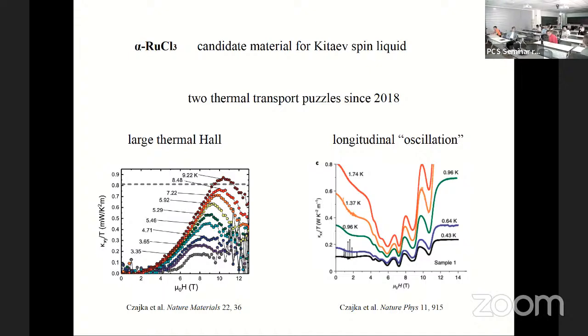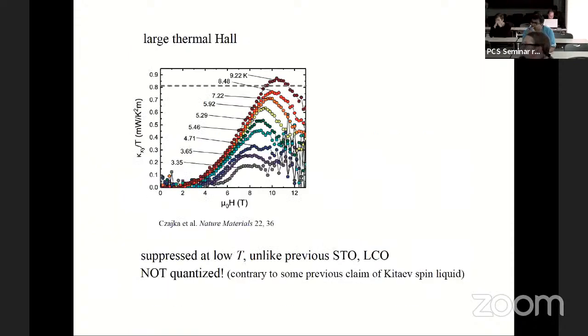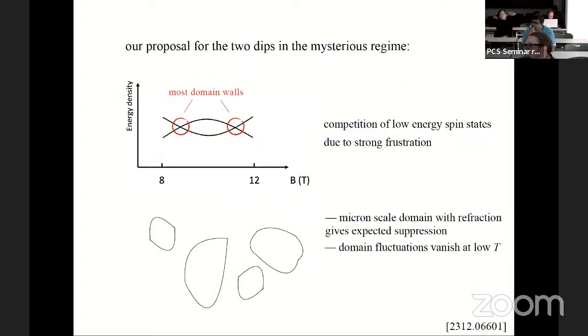So I have another question. You said that here, so can I think of these fluctuations as some sort of defect or not? As you can see, this domain wall formation, you can think of them as defects, but those are defects coming from dynamical degrees of freedom. But that was the mechanism introduced by Anderson, Halperin, and Varma, as I understood, no? No, those are point defects. These are extended defects. Right. So those are dynamical defects, but with low energy. Here the scattering is strong. They come from dynamical degrees of freedom, but the scattering is strong not because of dynamical resonance, but because the defects are just large. They are micron scale. So the phonons cannot then diffract.